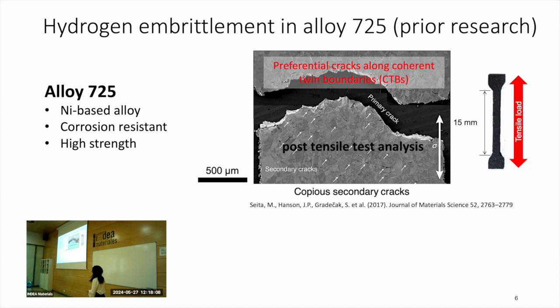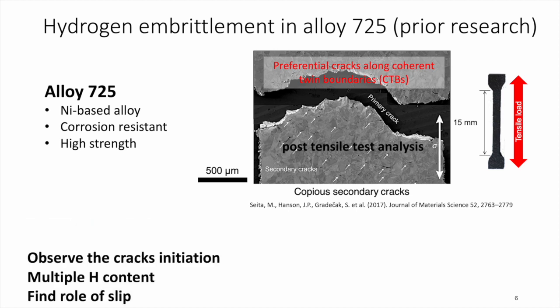But this is a post-tensile analysis, which means we see everything after it happens. The crack is already there, the crack has already initiated and propagated. We don't know exactly how it happens. And if you remember the question we had before, is the slip trace the cause or is it the effect, right? We still don't know what the role of the slip is. How can we observe the crack initiation? And by the way, all of these experiments have been done with only one hydrogen content. It's just a single charging condition. But what if we change the hydrogen content from low to high and see if there's any correlation?